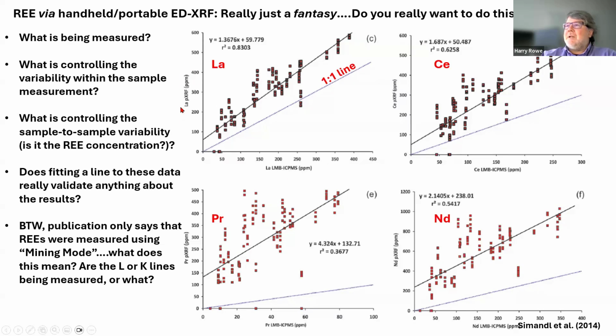And here's the lanthanum for XRF. It is, again, what value do you want? For the value that this sample has, you go anywhere from just over 200 to just over 300 ppm for that sample, 5 analyses of the same sample. This technique cannot measure, cannot quantify these elements using a typical portable XRF.